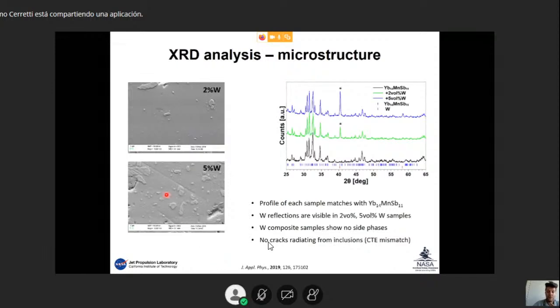Also here, from microscopy and X-ray analysis of the material, we can see that the materials are pure phase. From microscopy, you can see that the tungsten inclusions are well dispersed. And here, the scale bar is 1 micron, so we can see that the inclusions are well into the nanometer size, and we have some features that are a few micrometers big. And the nice thing is that we don't see any cracks propagating from the inclusion into the matrix.